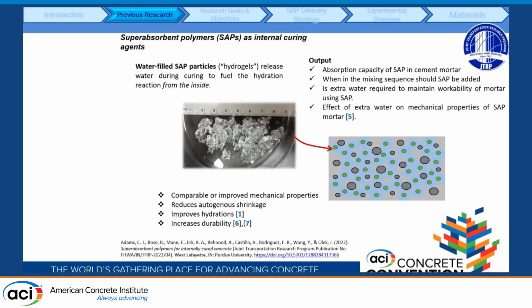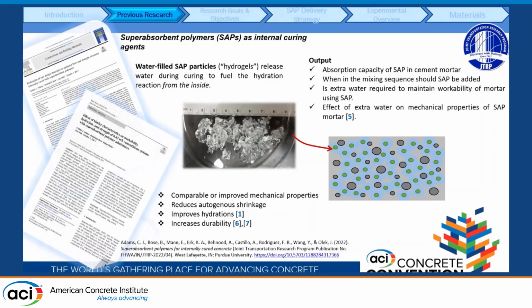Now, regarding this project, it's an offshoot of a previously conducted lab research we did, where we used the superabsorbent polymers in mortars, cement mortars, and some of the outputs were that we were able to get the absorption capacity and the mixing sequence of using superabsorbent polymers. Some of the results we obtained were improved mechanical properties, and it also reduces autogenous shrinkage and improved hydration.